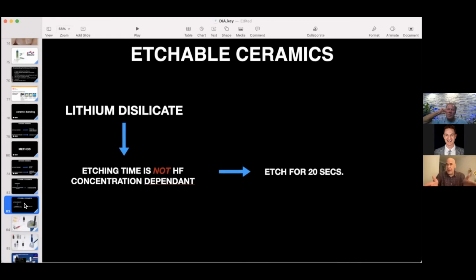So your bond strength, regardless of the concentration, as long as you etch for 20 seconds, is going to be the same. Okay? Don't call Ivoclar. They're going to sell you their etchant, which is fine. That's part of the game. I'm telling you, if you buy ultra dense hydrofluoric acid etch, which is at the high end, and by high end, I mean high concentration in the 9.5%, it's going to be fine. You're not going to have a problem. As long as you etch for 20 seconds, you're going to be super fine.